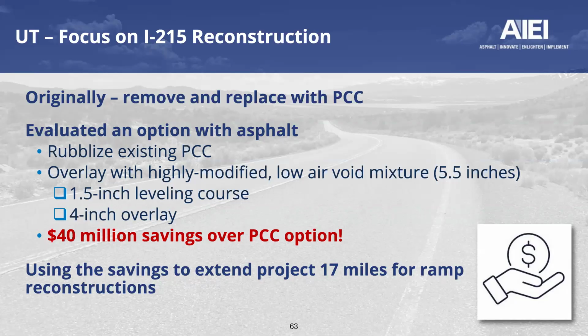The decision was made to do an alternate design, looking at rubbleizing the PCC in place and overlaying it with 5.5 inches of the highly modified material in 2 lifts, in this case, a 1.5-inch leveling course on top of the rubbleized material, and then a final lift of 4 inches. The upshot of the cost savings was roughly $40 million compared to the removal and replacement option.